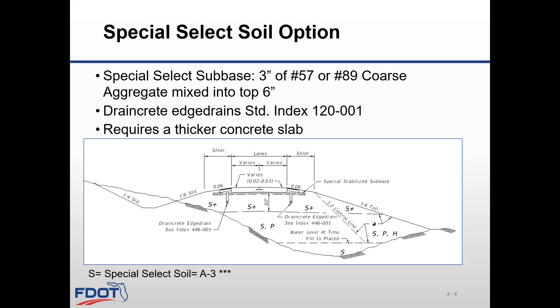More on this will be covered in Module 7 for pavement design widening. Even if this typical has been used in the past, construction can be more difficult due to the less stable material and problems encountered in the field with achieving the proper depth and permeability of the soils. This option also requires a thicker slab compared to the asphalt base option since it doesn't contribute to the structural performance of the slab.